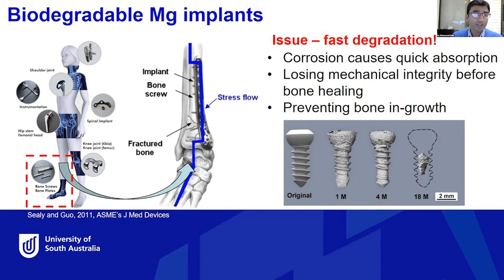However, the main concern with magnesium alloy is its fast corrosion, especially when it comes in contact with a saline environment. The degradation is caused by the corrosion process itself. As a result, the magnesium loses its mechanical integrity even before the bone healing is complete. Because of this, the bone implant performance is deteriorated, causing failure of the implant in the end, so there may potentially be a need for secondary surgery to fix it.